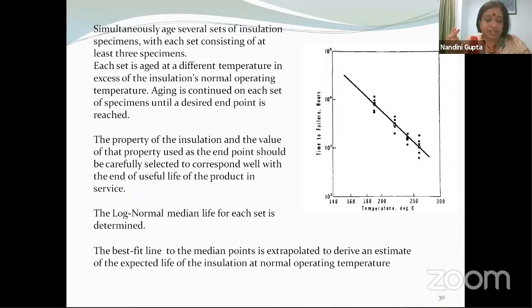So when you choose the aging test and you accelerate the aging test, you need to remember that you have the same conditions as in the field, which means the same failure processes must be there and no additional processes must come into the picture. So for example, if you're performing electrical aging test, we will discuss this in one of the sessions, we know that when space charge accumulates in a material, beyond a certain field, only space charge accumulates and then electrical aging occurs. So if you work below that threshold field for space charge accumulation, you're not going to have any aging due to space charge accumulation. So therefore, you cannot use those different fields for the accelerated aging test. So it is very, very important to be able to choose the failure indicator as well as the operating accelerated test values at meaningful values, keeping the physics in mind.